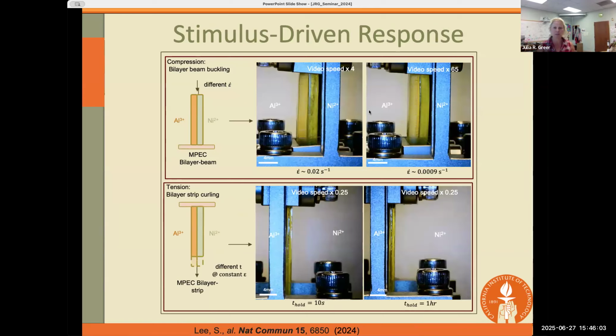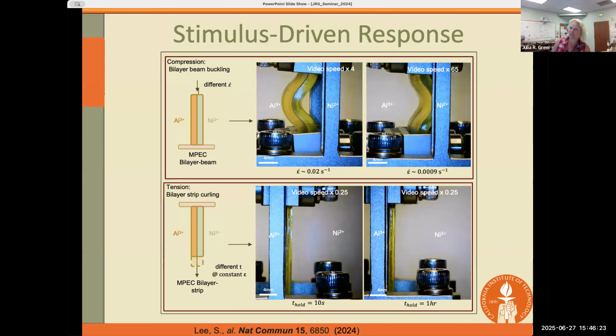What I'm showing you on the top is the compression experiment, where you can see this bilayer strip buckles, as we would expect, to the left. The deformation rate here is 0.02 per second. Now, if you conduct exactly the same experiment on exactly the same strip, but you really slow down your deformation, you can see it's still buckling, but now it's buckling fully to the right. The only difference between these two is the strain rate, which means how fast we are deforming them.